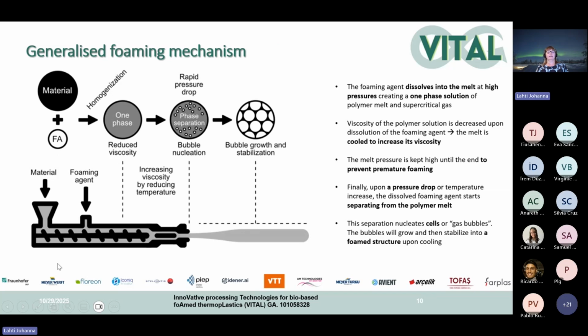Then this is a schematic picture of foaming mechanism in general. So you can see the basic structure of an extruder. You can see the hopper there where the polymer granulates are fed. And then if we are using this gas as a foaming agent, you can see that it is inserted almost in the middle of the extruder to the polymer melt. And then these agents that are used as granulates, they are of course fed with the actual polymer into the hopper. And then you can see the different phases, how the foam is created.